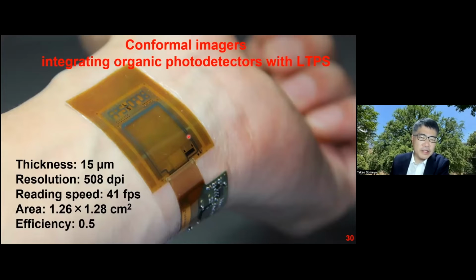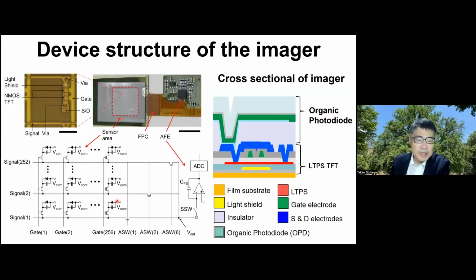So this is just single point detection, but now we succeeded in developing a two-dimensional array of photodetectors, integrating the organic photodetector and low temperature polysilicon active matrix. So we achieved a high spatial resolution over 500 dpi and high readout speed over 40 frames per second. So this is the circuit diagram and a cross section of the device structure. So we first fabricated a low temperature polysilicon thin film transistor active matrix that was originally developed for the readout circuitry for liquid crystal displays. And then we deposited the organic photodetector on the surface of the low temperature polysilicon.